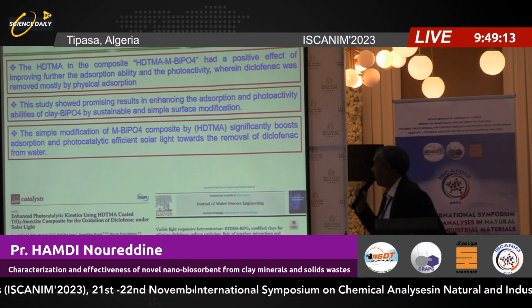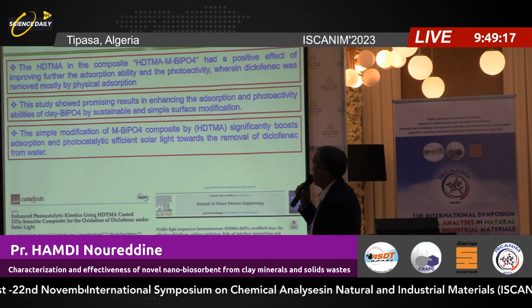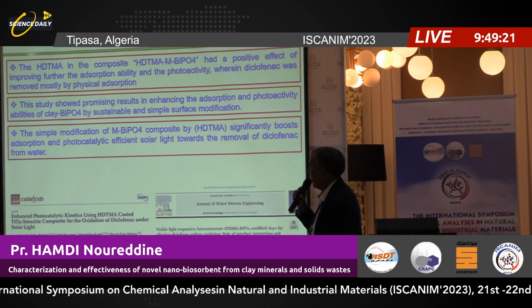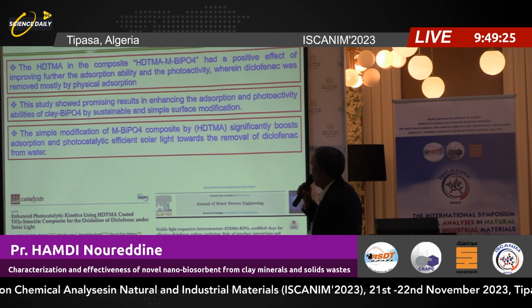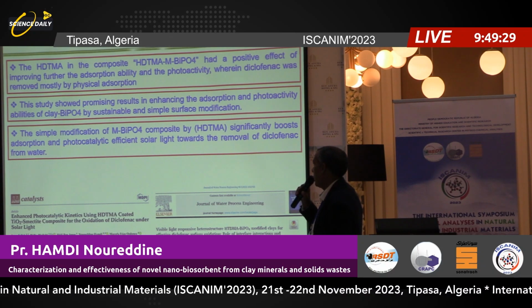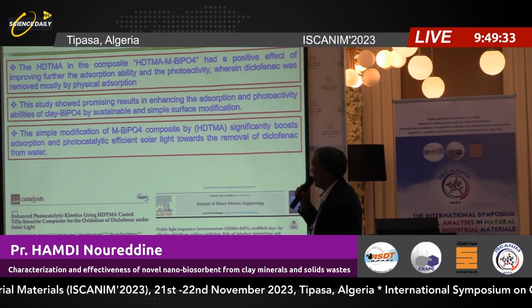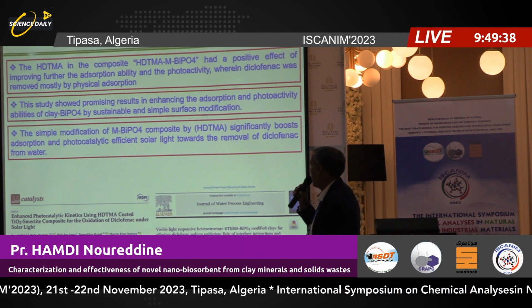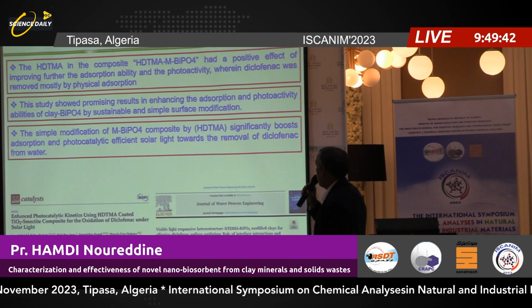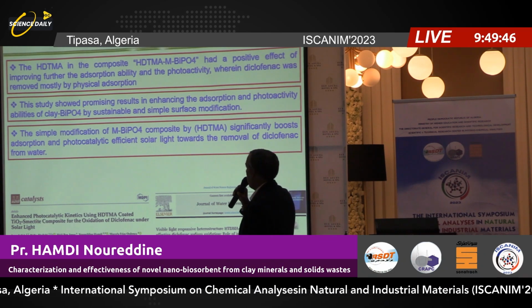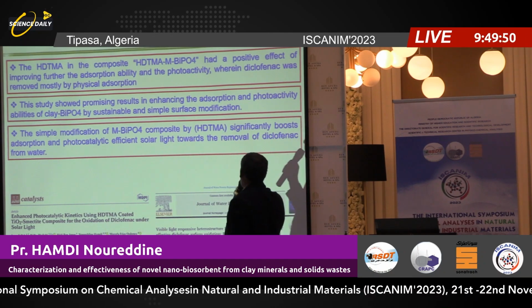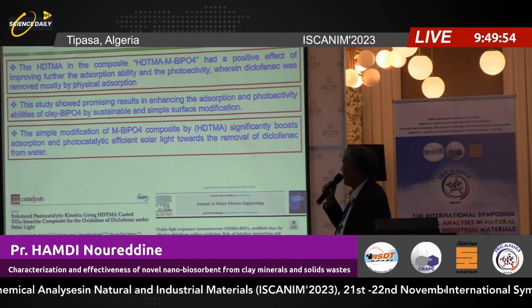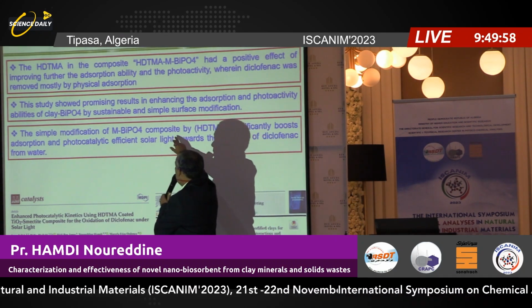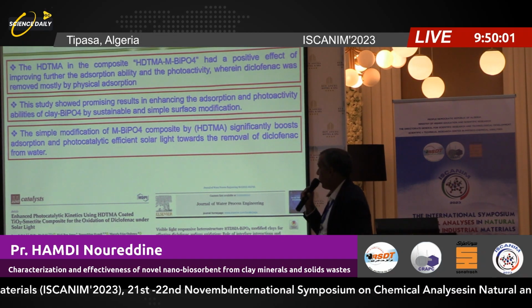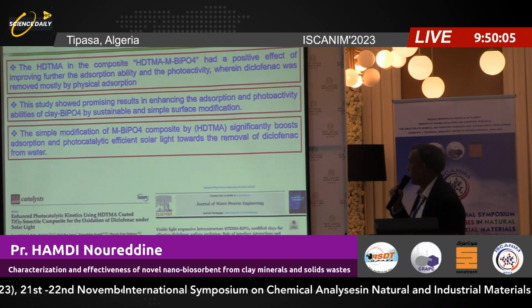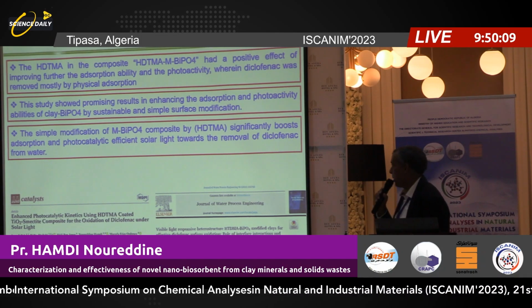And the conclusion of this part: the HTDMA in the composition of the composite HTDMA montmorillonite bismuth phosphate has a positive effect on improving further the adsorption ability and the photocatalytic ability, and the diclofenac was removed mostly by physical adsorption. Second conclusion: this study shows promising results in enhancing adsorption and photocatalysis ability of clay bismuth by sustainable and simple surface modification. The modification of the montmorillonite bismuth composite by the HTDMA significantly improves both the adsorption and photocatalysis effects with solar light. This is very interesting because we use only solar light to remove diclofenac from water. This work was published in two famous journals in the domain of water treatment and catalysis.